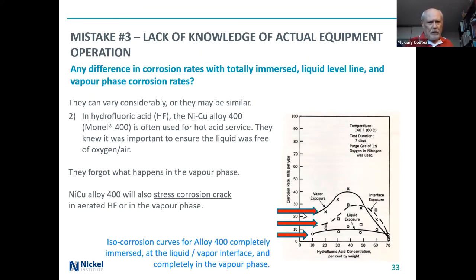And the top red arrow here shows in the vapor phase very high corrosion rates, depending on the acid concentration. The second red line, the middle one there, is that interface or liquid level line, a mixture of both. Sometimes it was in the liquid all the time, other times it was in the vapor part of the time. And finally, the continuously immersed exposure there. So you have to be very careful. And in this case, it was extra special because the alloy 400 will stress corrosion crack in aerated hydrofluoric acid or in the vapor phase.